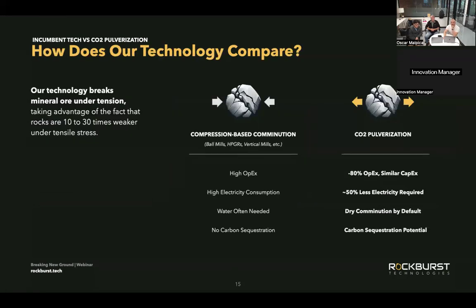Just to summarize, what we have observed experimentally, and as Cliff mentioned, extrapolated based on the simulations that we're doing, in terms of how we compare with compression-based comminution. This is what you see on the screen. In terms of CapEx and OpEx, again, too early to tell. However, the early estimates point to a potential future CO2 pulverization mill at about the same level in terms of CapEx as, say, a ball mill, but a lot less OpEx. And this is because we get rid of grinding media. It's a grindless comminution, to be honest, that we are offering here.